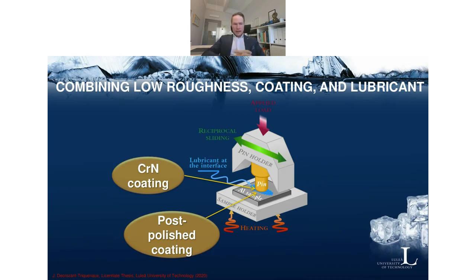Lastly, I want to show you what can happen when you combine several of these strategies. So in this case, we have back again the reciprocating pin on plate configuration in the Optimol SRV tester. So we have a pin that is tool steel where we have applied a chromium nitride coating. We have a flat aluminum sample, and we also have different surface topographies on the pin, and we have a lubricant between them also. And this is again a heated test, so we run the test at different elevated temperatures, around 300 to let's say 500 maximum. I'll only give you a couple of examples here. And the idea is to understand what surface topography, coating, and lubricant does together when you apply all of them.